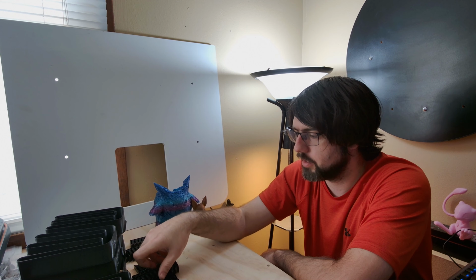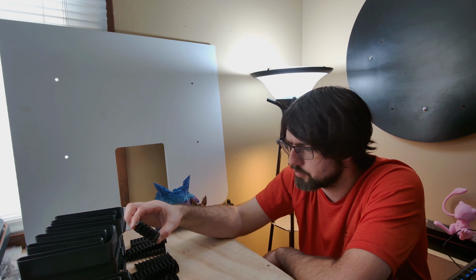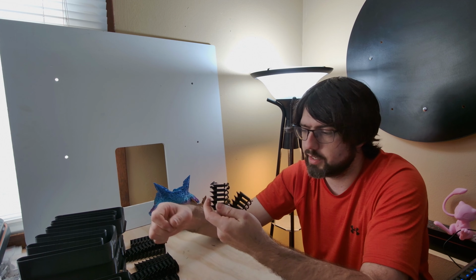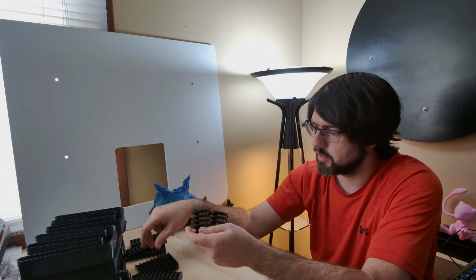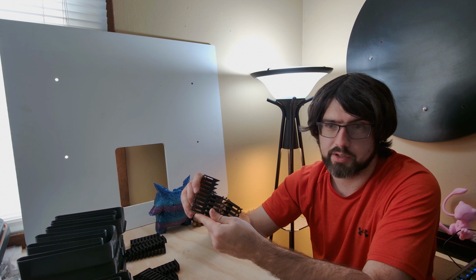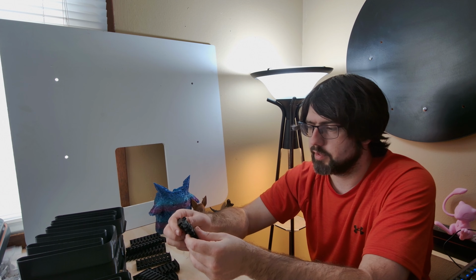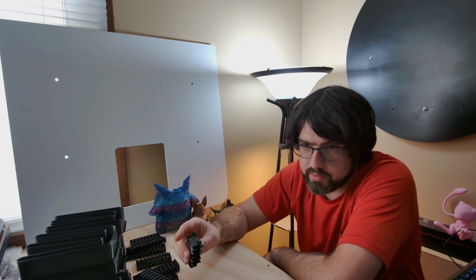Now on the next one, the temp tests. They were all pretty well as expected. The hardened nozzle struggled very hard with the PETG and the temp tower. The most that I could get it to print cleanly up to was about 235 degrees before the towers started breaking, which here I got 2 short towers, and here was the comparable test to how tall it should be, which is expected with the hardened nozzles. They obviously don't transfer heat near as fast or as well as the other options.